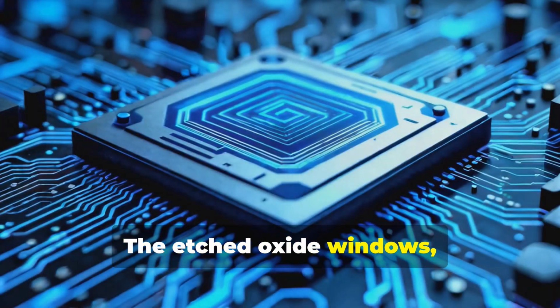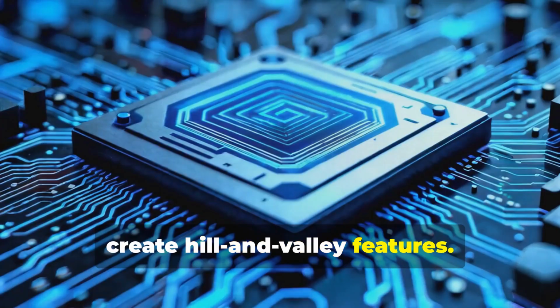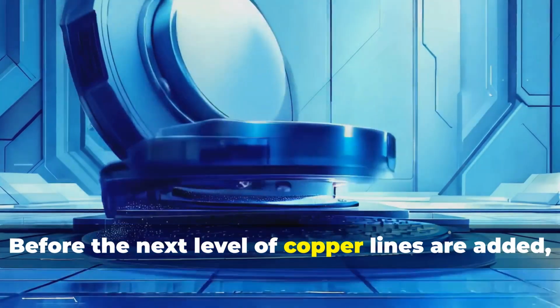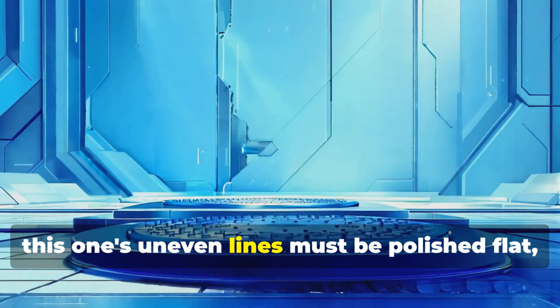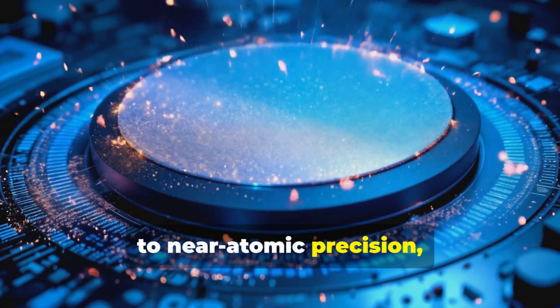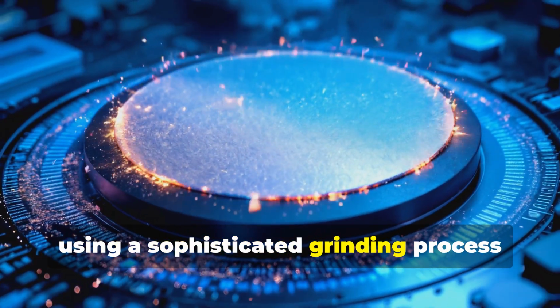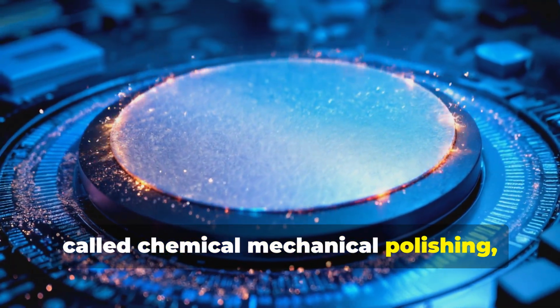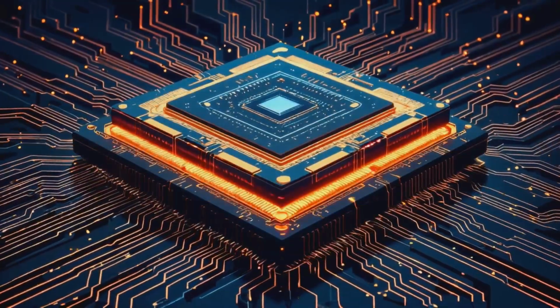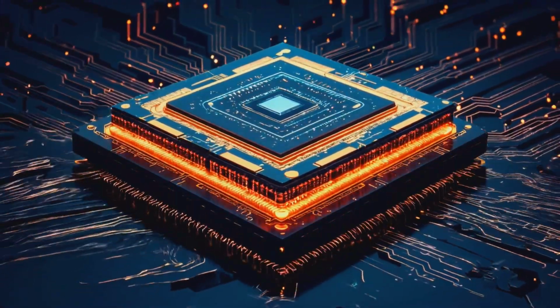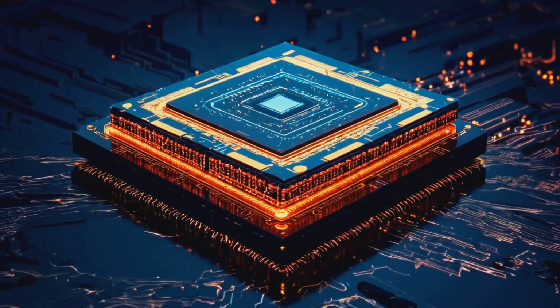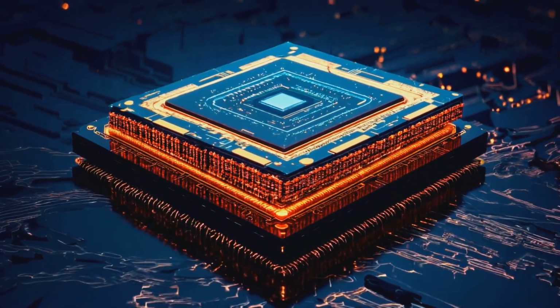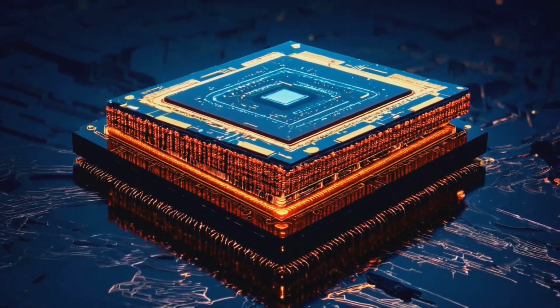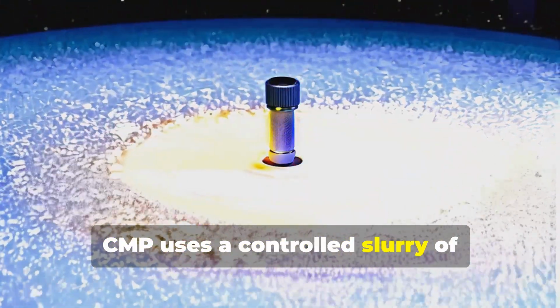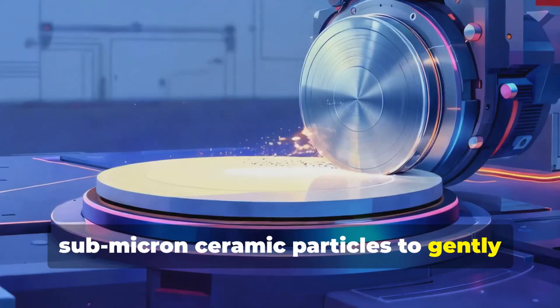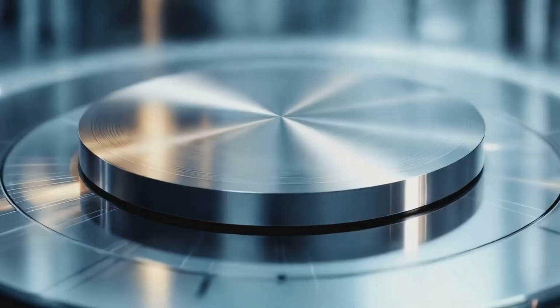The etched oxide windows, however, create hill and valley features. Before the next level of copper lines are added, this one's uneven lines must be polished flat to near atomic precision, using a sophisticated grinding process called chemical mechanical polishing, or CMP. CMP uses a controlled slurry of sub-micron ceramic particles to gently scrape and flatten the bumpy features.